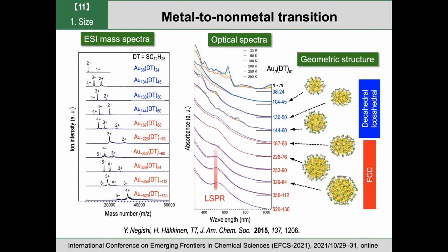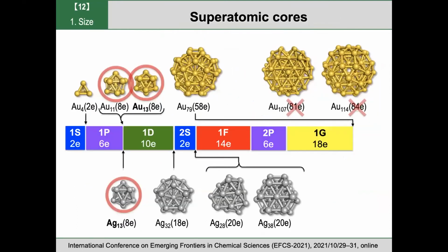And after that, our community discovered that these metallic cores, gold and silver cores, are formed within the organic layer. And if you count the number of electrons confined in these cores, 2, 8, 58, and so on, these numbers can be explained by the closure of the superatomic orbitals, as I told you. In the case of 58, these orbitals are occupied by 58 electrons. But for these largest particles, the electron number cannot be explained by a simple closure of the electronic shell.